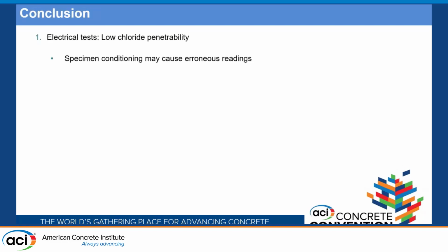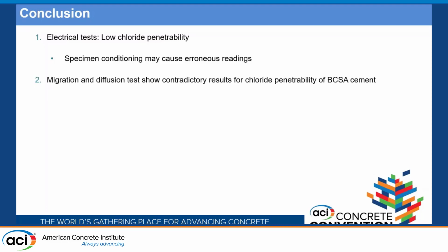Finally, I would like to conclude that the electrical tests have shown low chloride penetrability. However, specimen conditioning may cause erroneous results, as we observed for the bulk resistivity test. The second is that the migration and the diffusion tests show contradictory results for chloride penetrability of BCSA cement. The third is that the corrosion performance of BCSA cement improves with curing age.